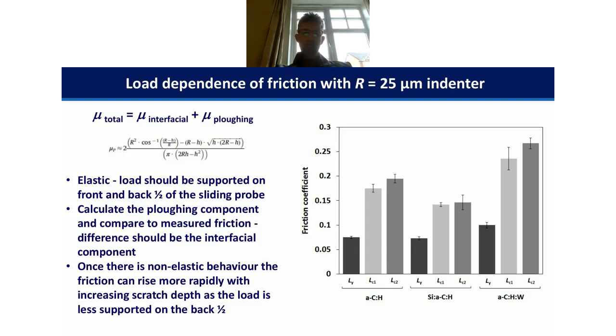So we can also measure the friction throughout these tests. And when we do that, we can understand how the friction varies as a function of load by applying these two-term equations, where you split the measured friction into an interfacial component and a ploughing component, which is depth dependent in the system.